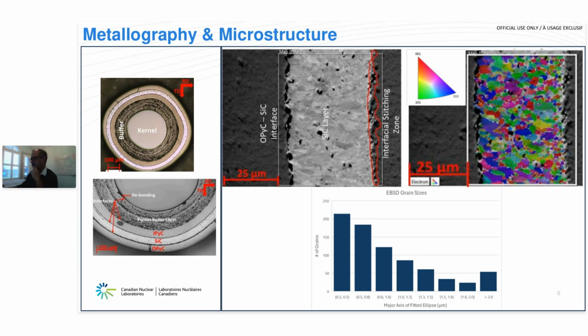What you see in this EBSD map towards the right, which is the interface with the inner pyrolytic layer, is that the grain size of the silicon carbide coating is actually smaller, and the grain size does increase as you go from left to right, from the inner pyrolytic side to the outer pyrolytic side of the particle itself within the silicon carbide. And at the bottom, you see the grain size distribution. Typical grain size near one edge of the coating is between 0.3 and 0.5 microns. And as you go towards the other end of the coating, the grain size becomes extremely large, sometimes greater than a micron, or sometimes even 2 microns or so.